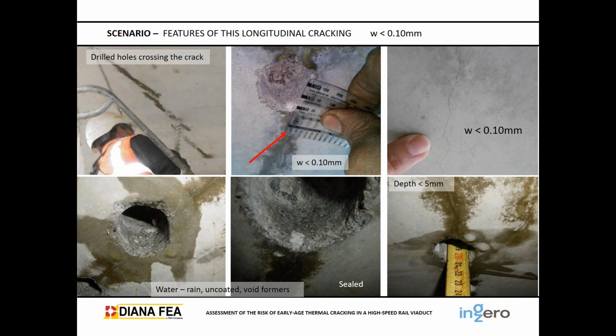When we drilled the holes, there was water, as we can see in the lower photograph. Well, in the north of Spain it's mostly rainy, and there had been rain during the placement of the void formers. The construction company told us that those polyethylene void formers were wet when they placed them onto the deck. So as we drilled the holes, the water came through these void formers. Also, we can see in the fifth image that it was sealed. The cracks were very small and they don't go deep into the deck. If you see the white dot over there, it had already been sealed. Okay, these are the photos we got of the cracks.